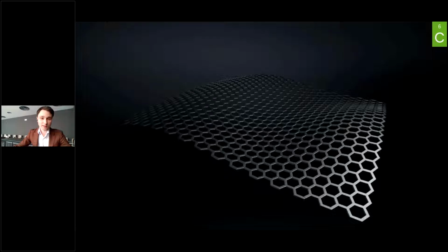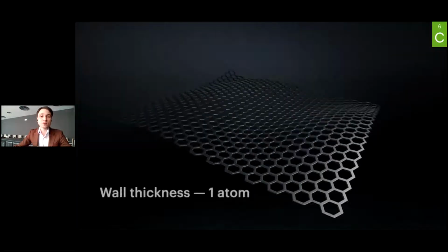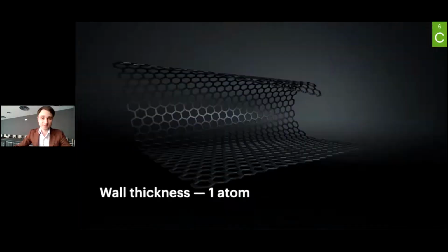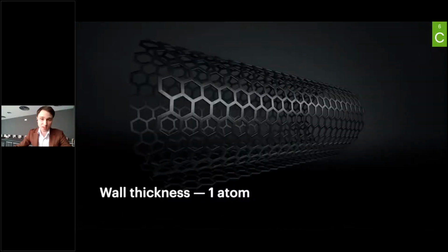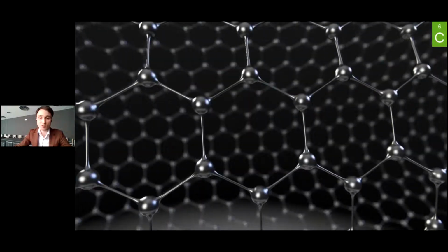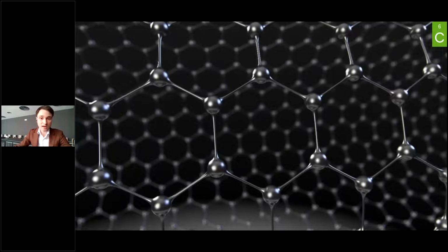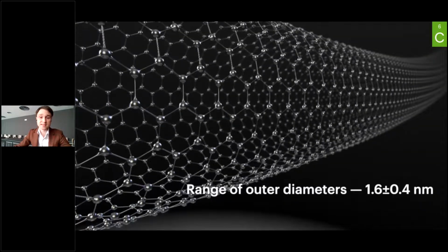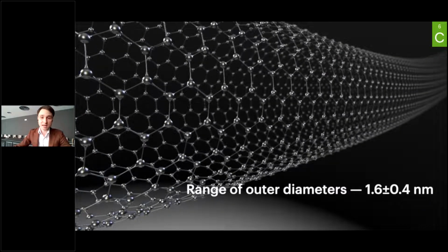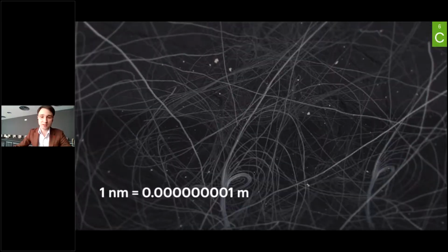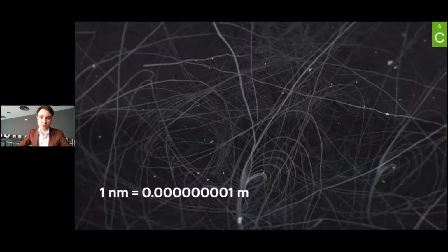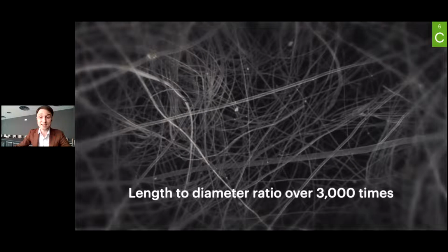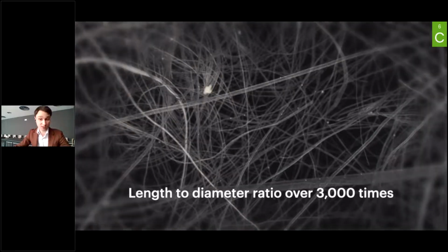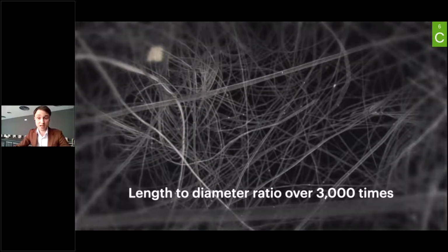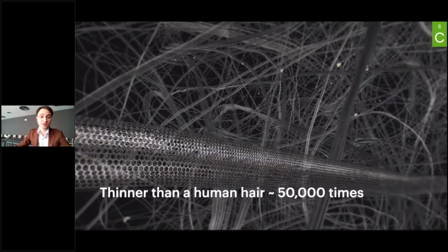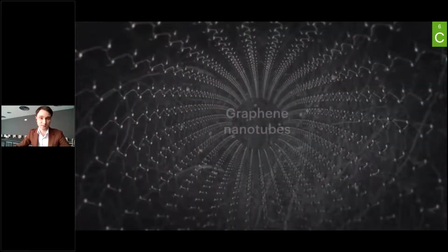So moving forward, I would like to tell a couple of words about single-wall carbon nanotubes itself. Single-wall carbon nanotubes or graphene nanotubes, which have a trade name TUBALL, are tubes with a wall thickness of a single atom of carbon. A diameter is about 1.2 nanometers and length about 5 microns. This material has extremely high aspect ratio, which is a ratio between length to diameter, which leads to unique performance of graphene nanotubes because they are very flexible.